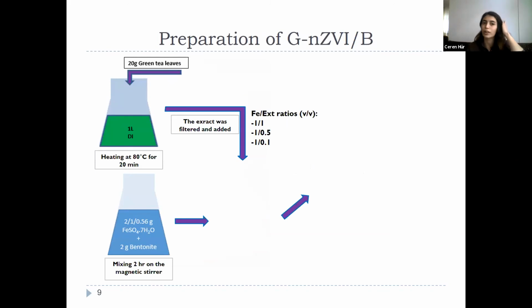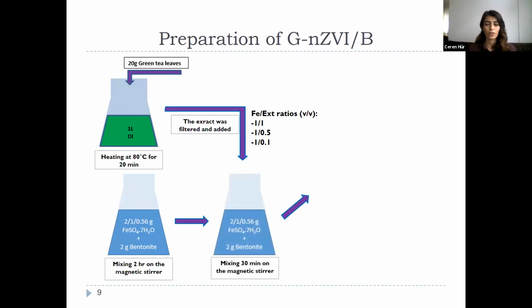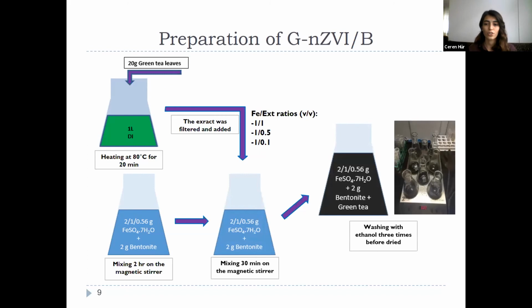20 grams of green tea leaves and 1 liter of DI water were mixed and heated up to 80 degrees and kept for 20 minutes. Then this mixture was cooled and filtered. 2 grams of bentonite was added into the iron solution that included different iron masses. This mixture was stirred for 2 hours. The green tea extract was added into the solution and stirred for half hour. Different volumetric ratios are worked. The color of the mixture changed to black due to formation of iron nanoparticles.